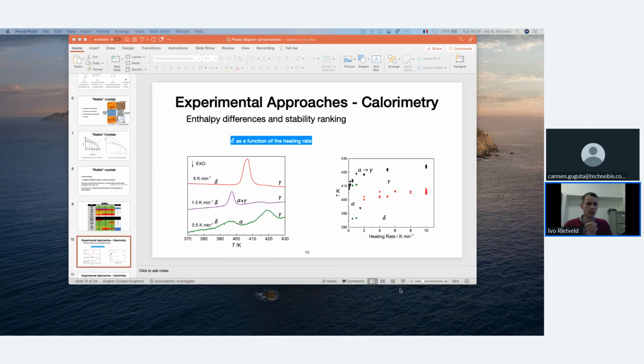So here, and this I think is rarely done because it's just a lot of work, but we used vapor pressure measurements. And I would say, in a sense, we're lucky with the pyrazinamide because it is so reluctant to transform, and it takes a long time in the DSC. You have to heat up at very high temperatures before you have actually the transformation of one form into the other. Therefore, it is relatively easy to use vapor pressure because the system stays intact. And that allowed us to do the vapor pressure measurements for all four forms. Here you can see the beta form, there the delta form. Then we have the gray gamma form.